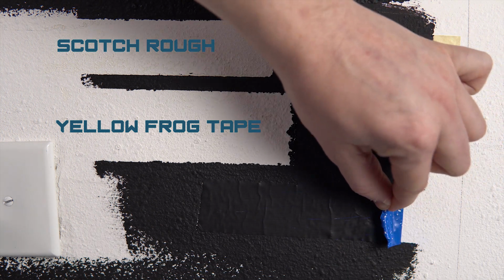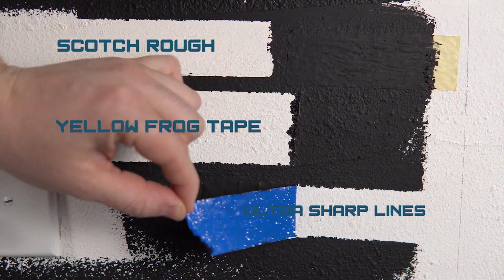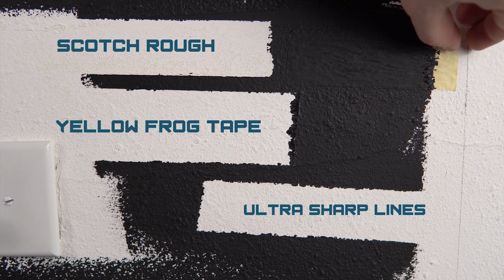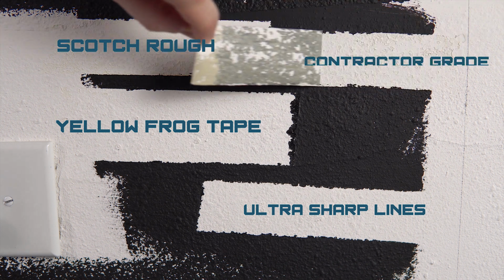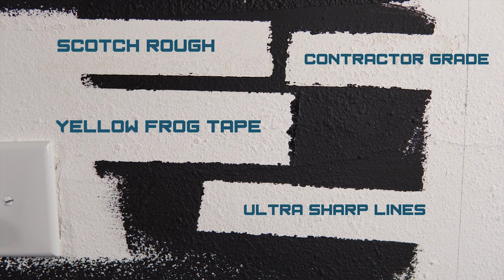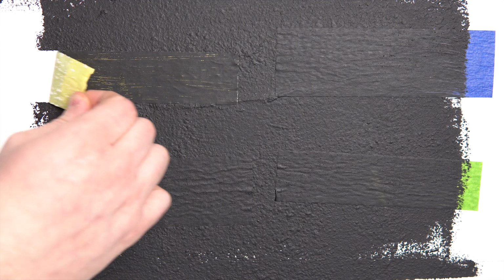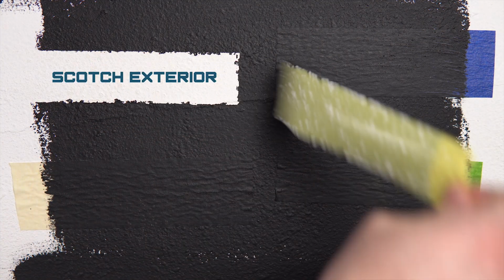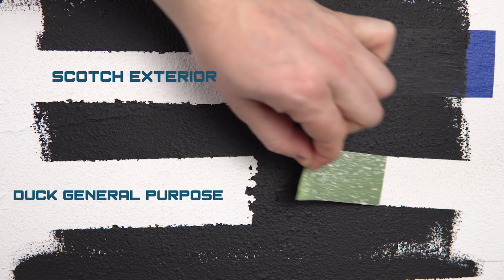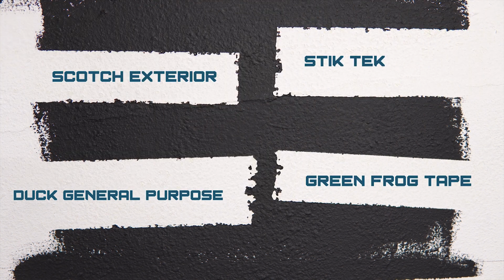The Scotch Ultra Sharp Lines has various places where the tape appears to have lifted, but the general contractor's adhesive seems to have really stuck to the wall, causing it to pull away paint and some of the texture. Although the Scotch exterior surface felt identical as the previous test, it still performed poorly. The Frog Tapes don't appear to have been affected beyond the expected.